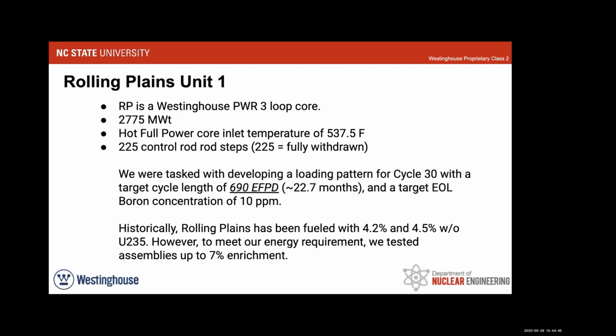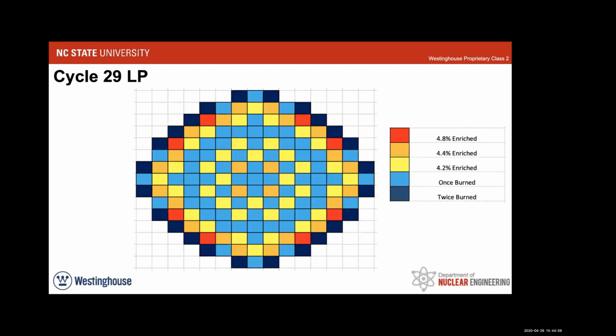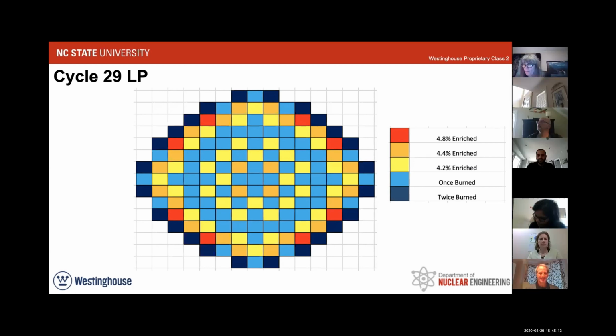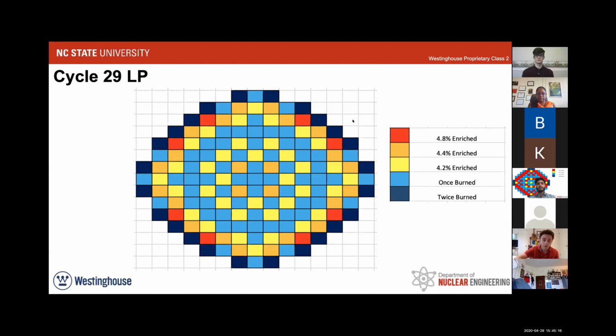And historically, Rolling Plains has been fueled with 4.2 and 4.5 enrichment. However, to meet this extended cycle length, we had to test with assemblies up to 7% enrichment to meet that cycle length. And so this is what we were handed off with. This is cycle 29, the previous cycle with the 4.8, 4.4, and 4.2% enriched. So you can see that with this lower enrichment setting, the core interior is more of a checkerboard, and there's a ring of once burned fuel and a thinner ring towards the periphery of the higher enrichment.